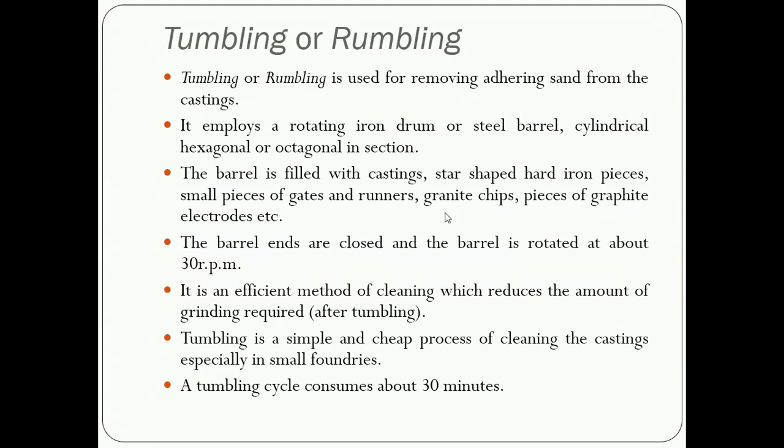Now the barrel ends are closed and the barrel is rotated at about 30 rpm. It is an efficient method of cleaning which reduces the amount of grinding required after tumbling.